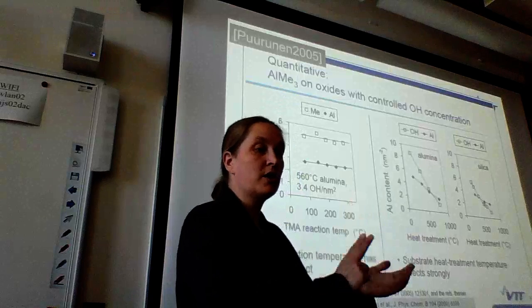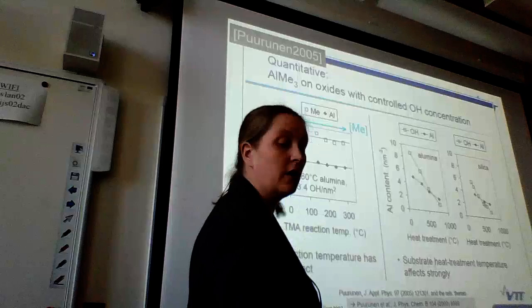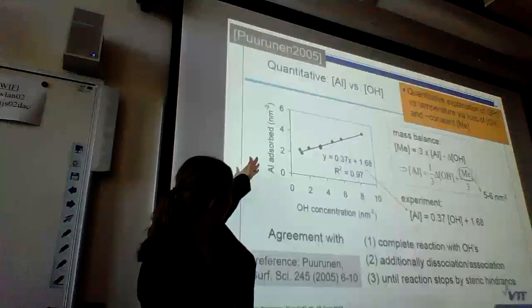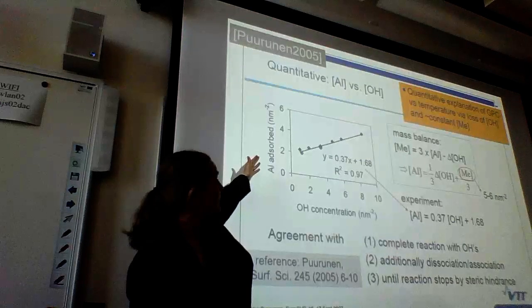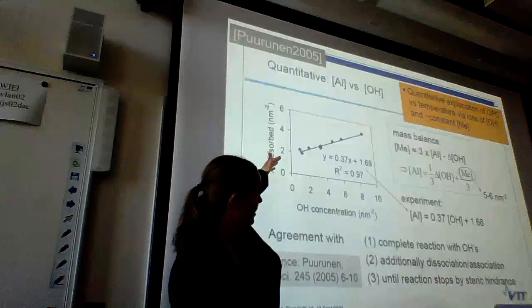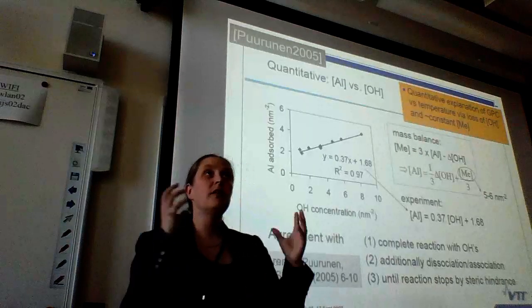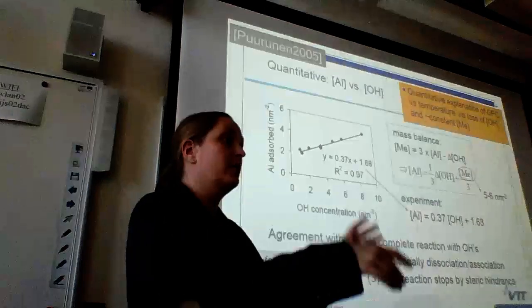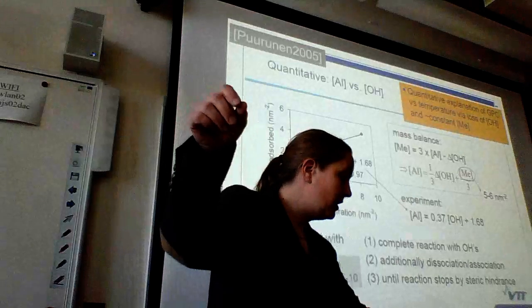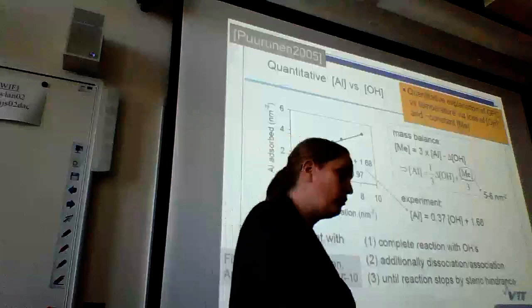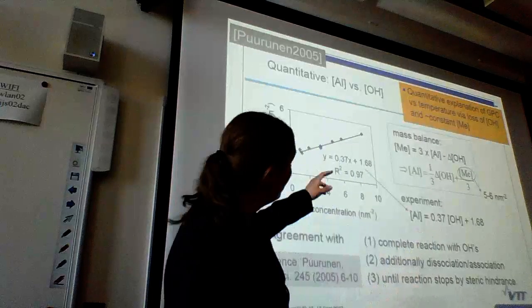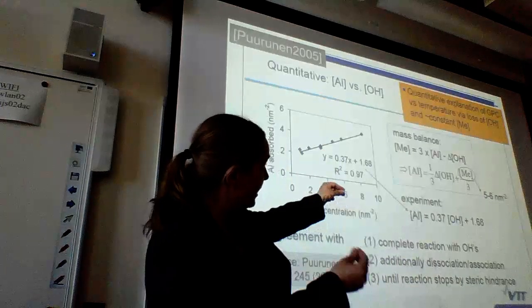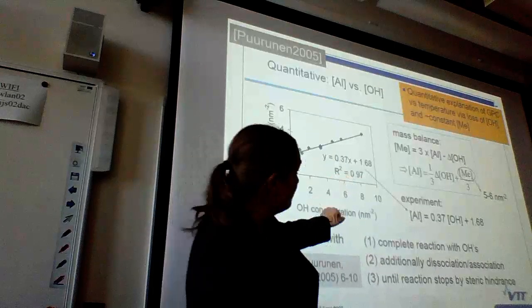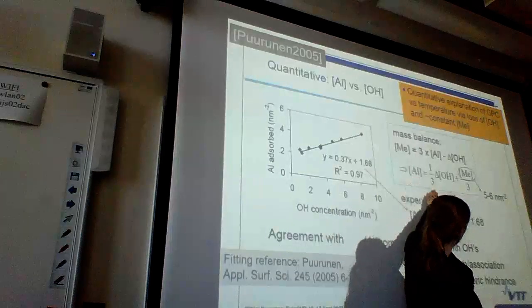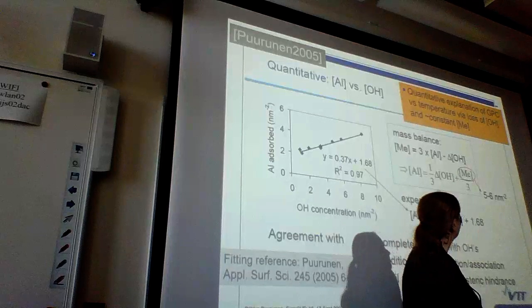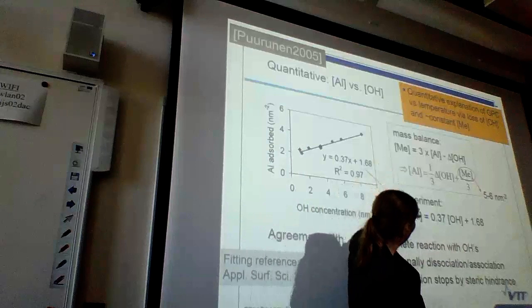But we know here all of them, OH, aluminium, metal group, so you can actually plot this. You can, of course, plot this amount of aluminium adsorbed, which is directly proportional to the growth per cycle, as function of OH group concentration. You get a nice straight line. If you think of the mass balance, you have a trimethyl aluminium molecule. It comes to a surface with its 3 methyl groups. It sees an OH, a methyl group goes and reacts with the OH and leaves. And the rest goes there with one less methyl group. So the amount of methyl groups is exactly 3 times the amount of aluminium groups adsorbed minus the amount of OH groups reacted. This one you can rewrite. You get aluminium content, that is 1/3 of the amount of OH groups that reacted, plus 1/3 of the amount of metal groups there. So you can compare that one with an experiment and you see that they are the same.